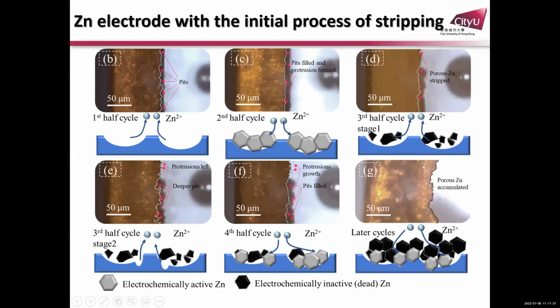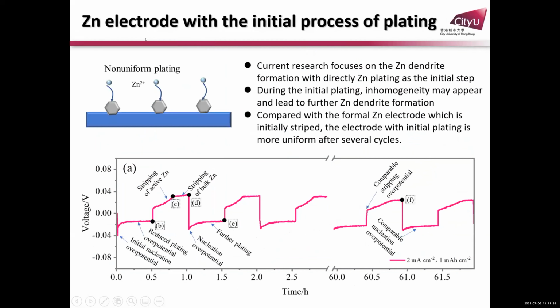We call this dendrites. But if you go for plating first, that means the zinc is not stripped first, it's plated first. When we study this process, you still have stripping of active zinc, stripping of bulk zinc, and plating with nucleation overpotential for the plating. So after a certain time, the behavior will be slightly different.